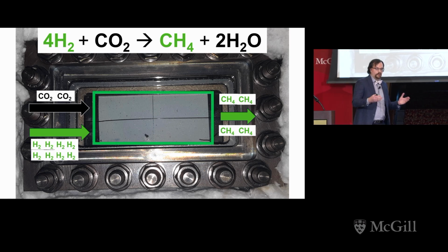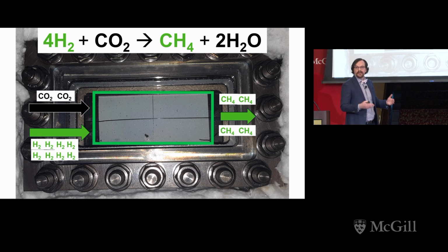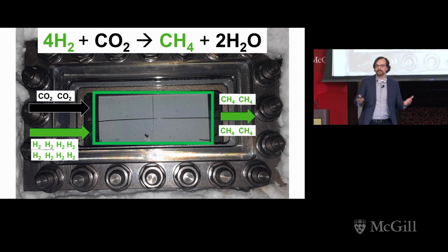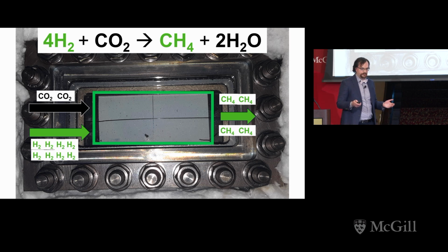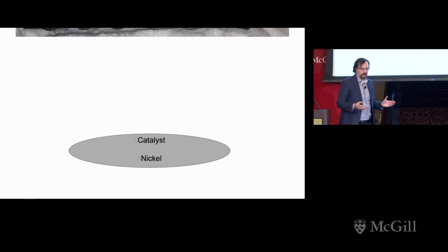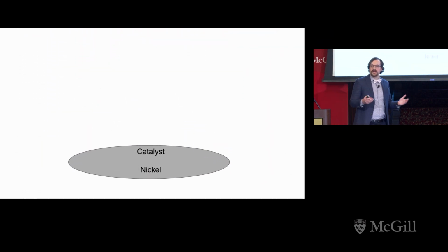In order for CO2 methanation to work at this temperature, we need a material that can increase the reaction rate. We call this a catalyst. In our case, I am using a nickel catalyst. The reason is it's actually fairly cheap. Its downside is it unfortunately takes a higher weight percentage, and also it usually reacts at a higher temperature. However, due to the cost benefits, it's the catalyst I decided to use.